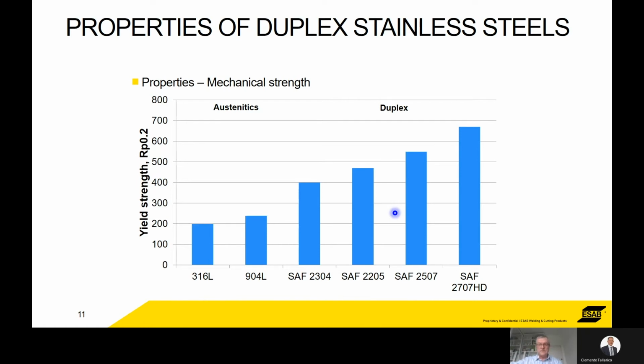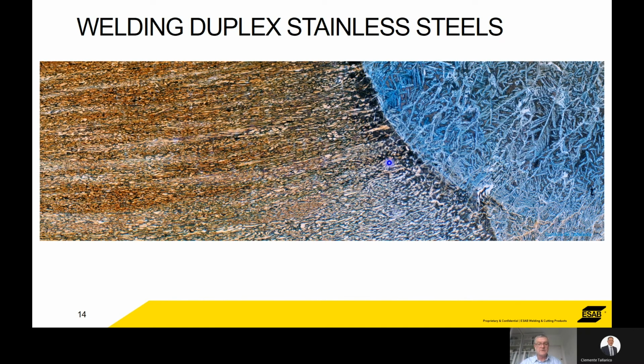If we look at a micrograph of a weld, this is the fusion line, base metal over here. This is a nice duplex material. You can see nice fine grains. It's a nice balance between the austenite and ferrite, nice grain size. As we get into the heat affected zone, the grain size is getting bigger, but you've still got a duplex structure, a nice mixture in the structure. And similarly with the weld. The weld's obviously got bigger grains. This has been molten and frozen, but you've still got a nice structure. So this is what you're trying to achieve when you are welding duplex stainless steels.